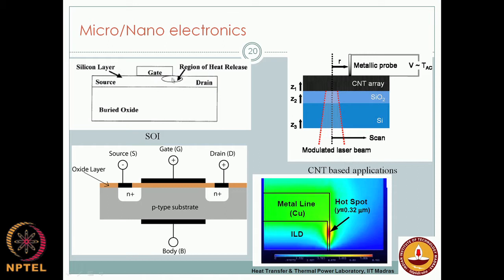So, this results in the generation of what we call hotspots. Localized hotspots. All this is local thermal non-equilibrium. Everything is a non-equilibrium process here, and once the hotspots are generated, number one is the prediction of these hotspots. If you use Fourier's equation at these length scales, you will usually under-predict the hotspot temperature as well as the heat fluxes. So, it will fail at this particular scale.